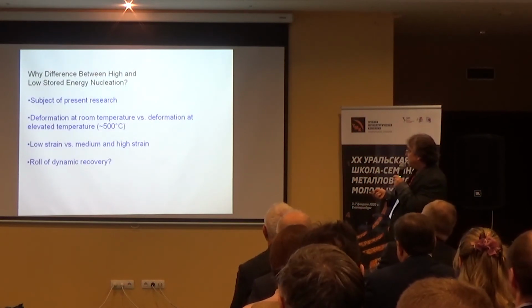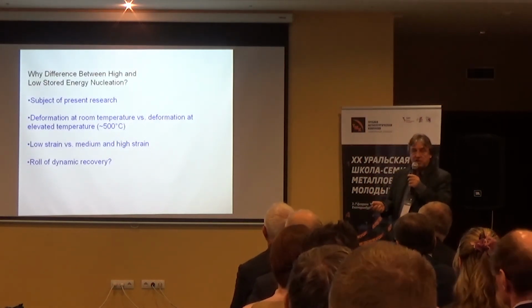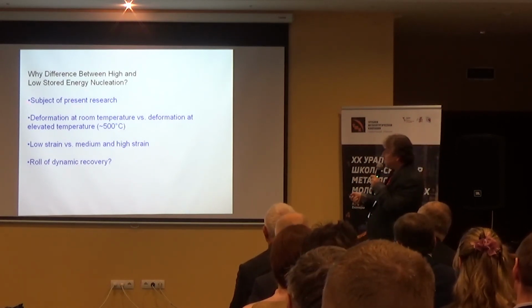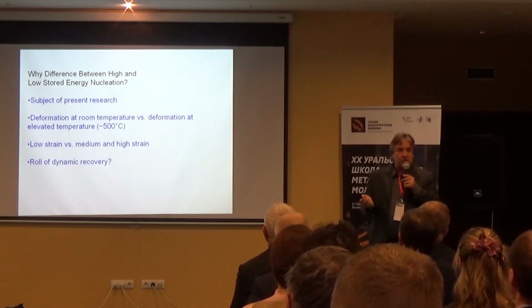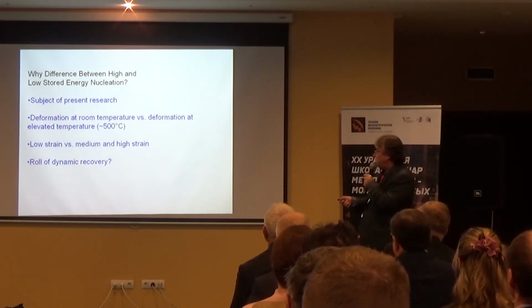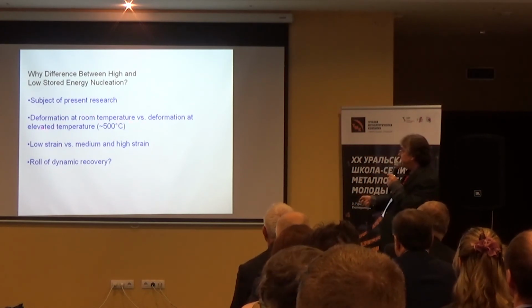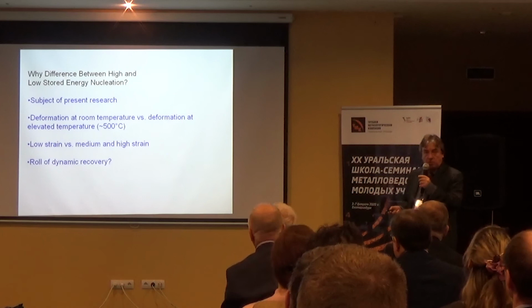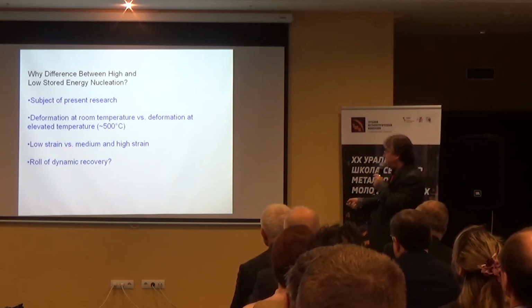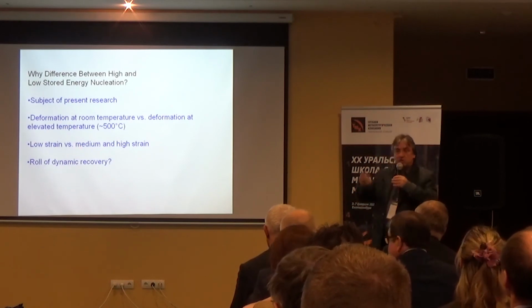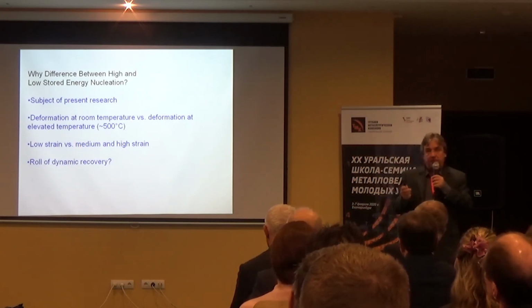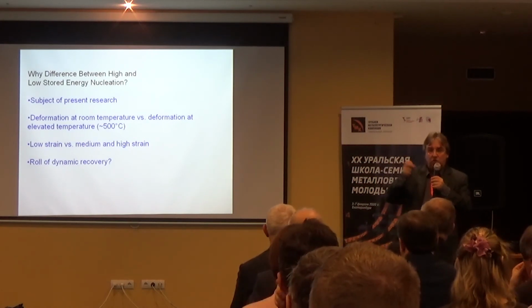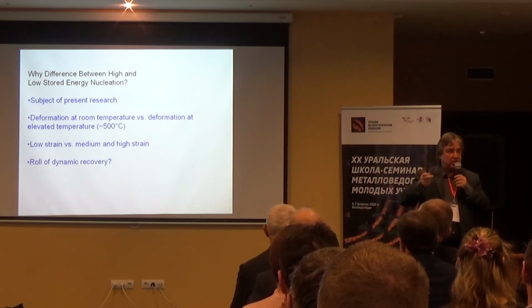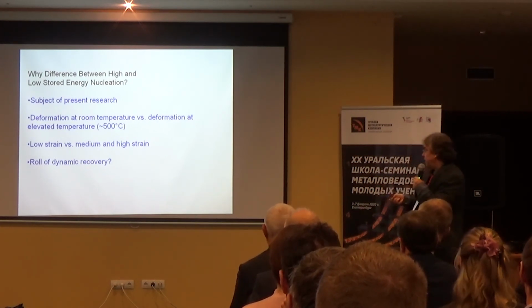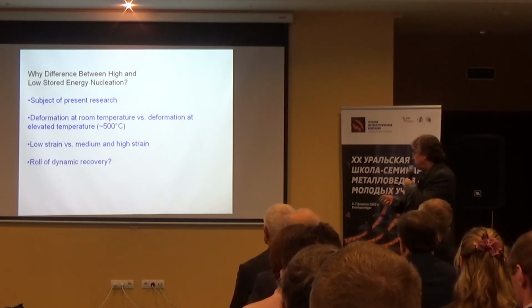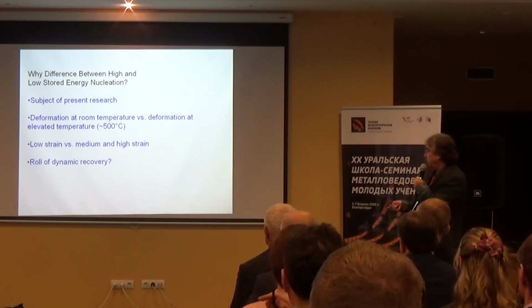Okay, so why is there a difference between high and low stored energy nucleation? Well, this is the subject of present research. I don't have a conclusive answer to this question. But for sure, deformation at room temperature versus deformation at elevated temperature plays a role. And low strain versus medium and high strain during rolling also plays a role. Because I didn't emphasize this, in the asymmetric rolling experiments, the total strain accumulation was much lower than in the conventional rolling process. And I don't have time to speak about it, but we could also discuss the role of dynamic recovery.